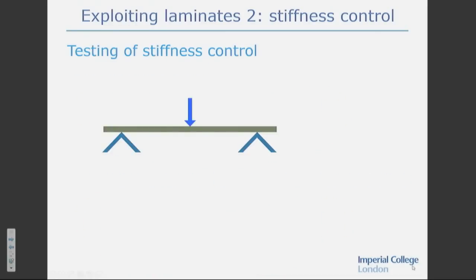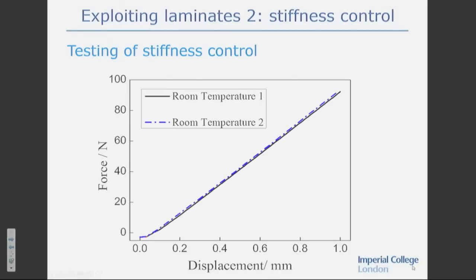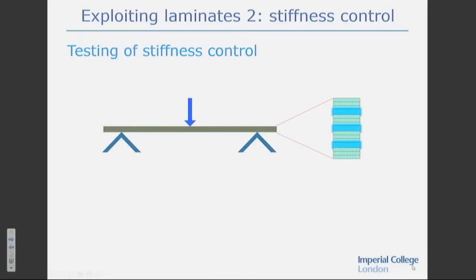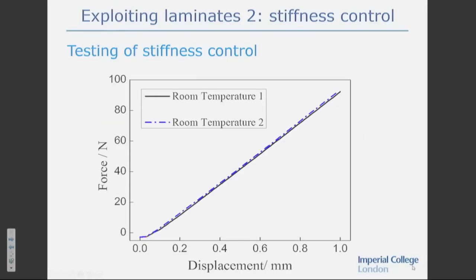So we've done this. We've made these composites. This is a test we've done, a bit like the test Jing did, but we did it in the lab in a test machine. It just consists of composite layers interleaved by these polystyrene layers. In this case, the thermoplastic was a polystyrene. So this is the force displacement response. We did 2 tests at room temperature here, and they're identical response. Then we did a test at an elevated temperature, actually at 120 centigrade, and there's the response. We've lost over 95% of the stiffness here.